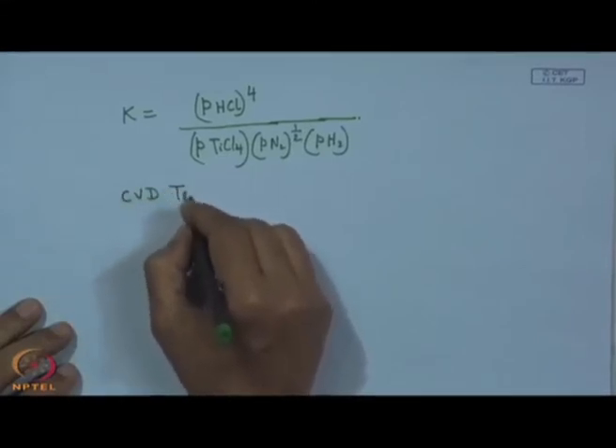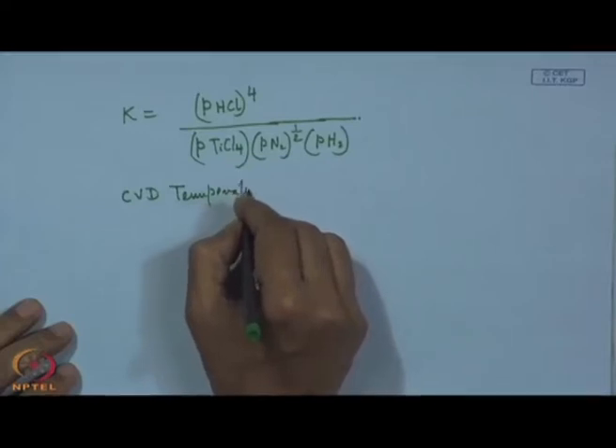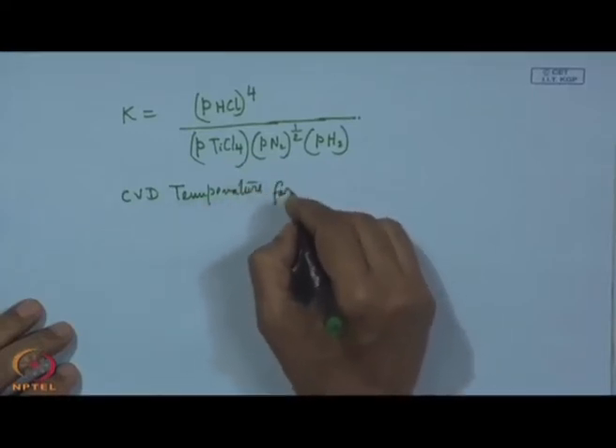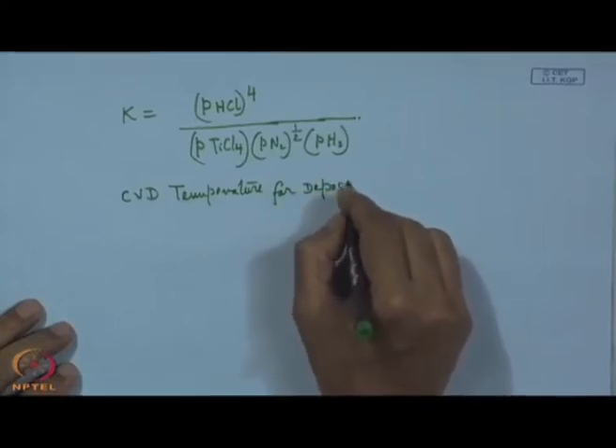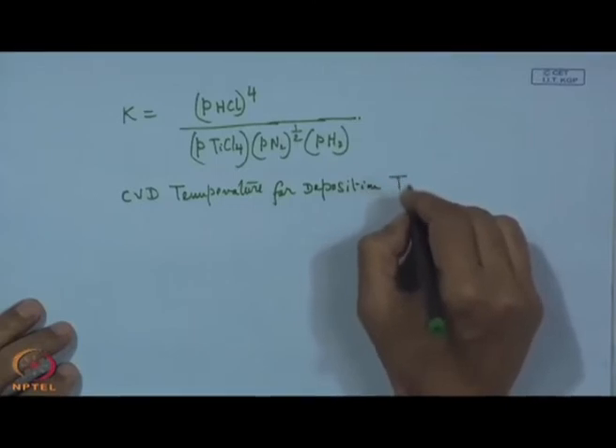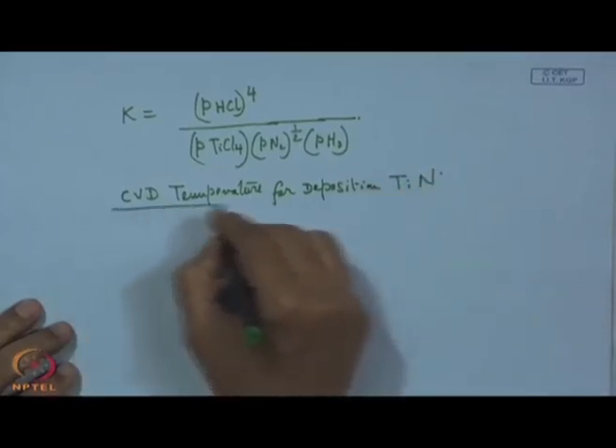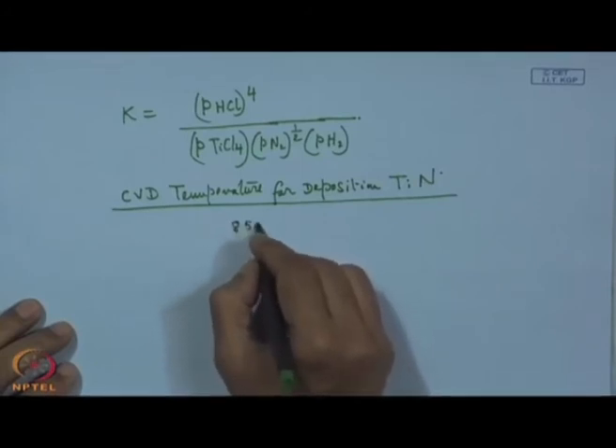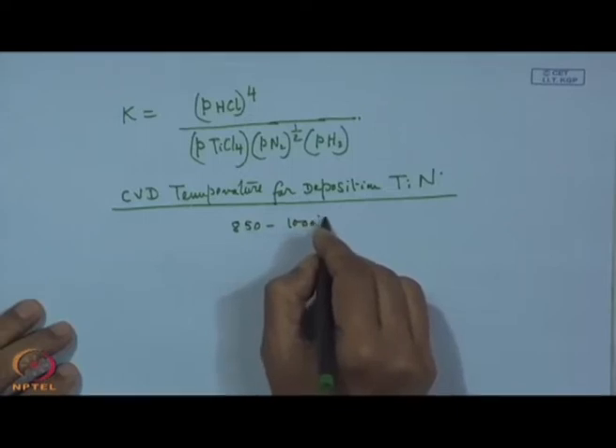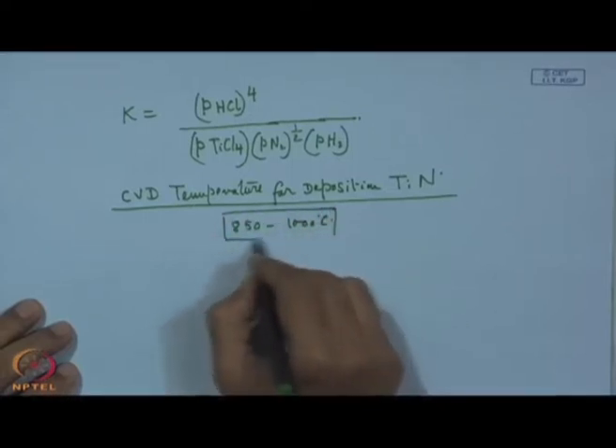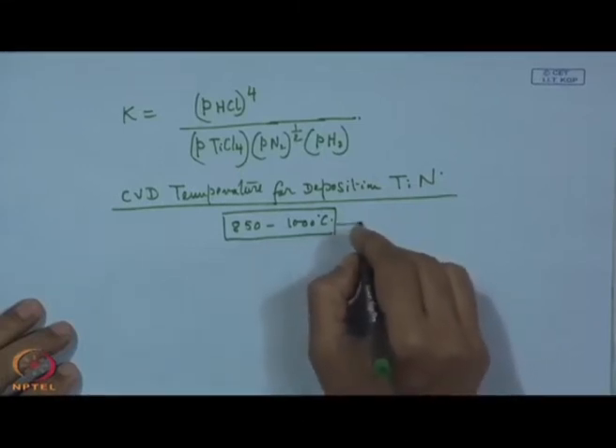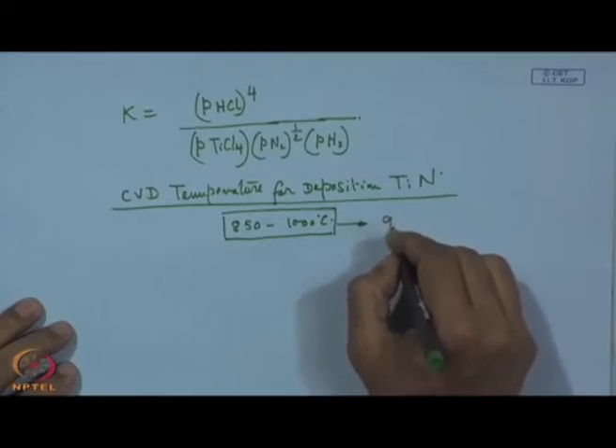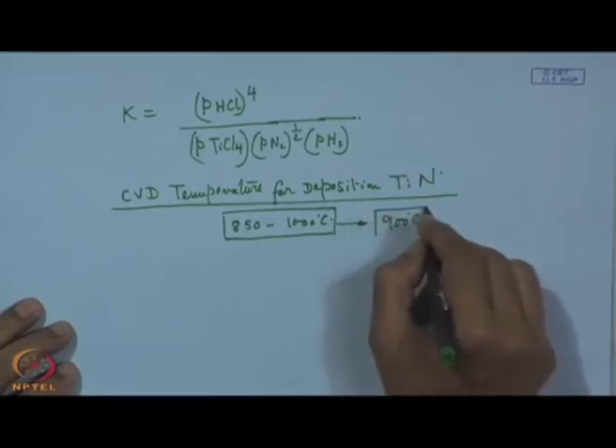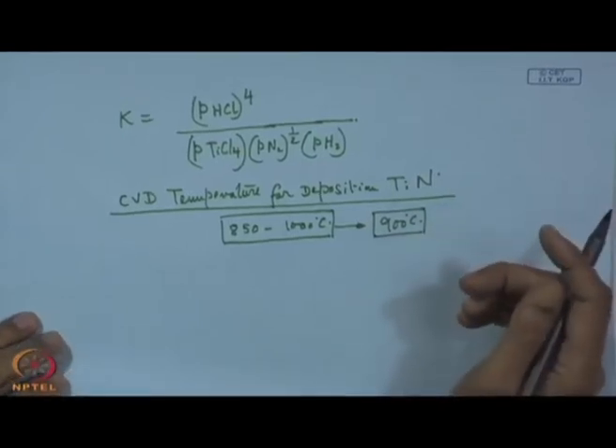Now, from experience, it is known that this CVD temperature for deposition of TiN ranges around 850 to 1000 degree centigrade. It can be done pretty well, and in industrial CVD, in many applications it is around 900 degree centigrade, which is carried out on a commercial scale.